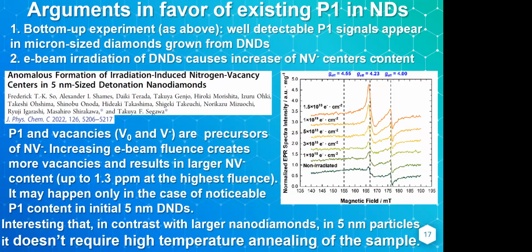And I've seen the same thing. If you grow a silica shell around the particles, I've not tried this on, say, detonation, but if you grow a silica shell, you see a considerable reduction in the intensity of that central line in the EPR spectrum. So something interesting is happening, obviously at the surface, which means that those centers were accessible to chemical interactions. At least some of them. Yes, I'm sure there's some on the surface, but not all of them.